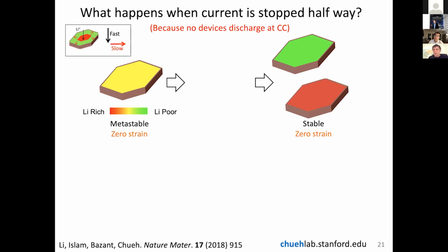So what if you take lithium iron phosphate in its metastable state, so say lithium 0.5 iron phosphate, which means you're in the miscibility gap. Now, when you have a high current, that means you don't phase separate. So I'm showing this on the left as yellow, okay? So you have no phase separation, and you stop the current. When you stop the current, the system will naturally want to phase separate. And it turns out there is a very interesting pathway for phase separation, which is to park all the lithium in half of the particles while keeping the other half free of lithium. The benefit of this is you don't form a phase boundary. So this basically tells you that the phase boundaries are pushed out by parking lithium in half of the particles.